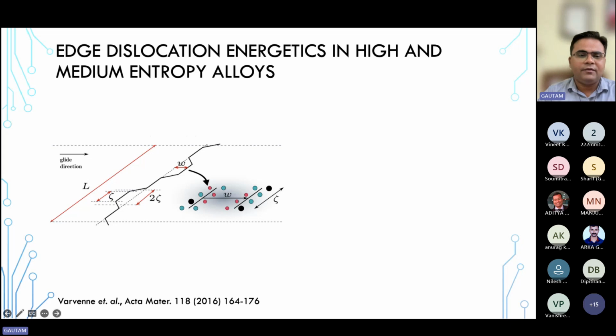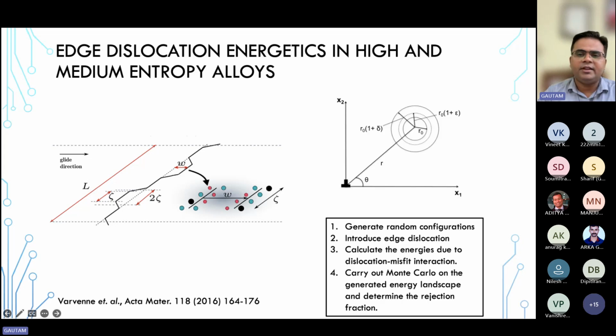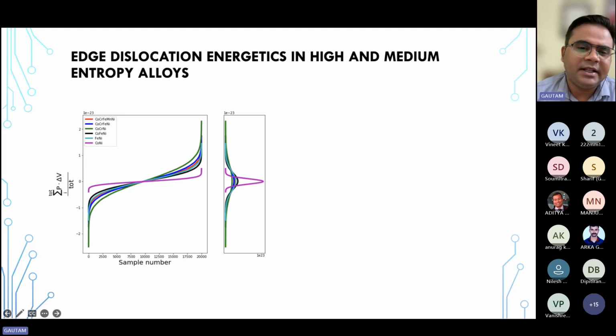So we developed a simpler model where we generate a random configuration and introduce an edge dislocation into it. Why edge dislocation? Because we are talking about strengthening due to the volume misfit, and we calculate the dislocation misfit interaction with the pressure volume term. We did it for some configurations and then carried out Monte Carlo on top of it. So if you see this number, for the same number of configurations, you get some kind of a distribution of energies.